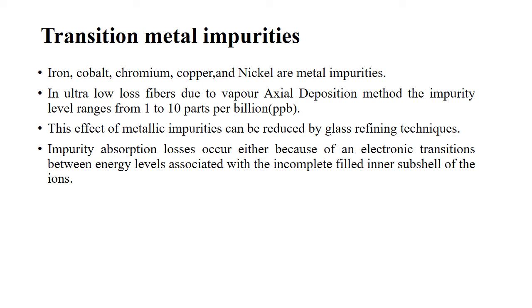The impurity absorption losses occur either because of electronic transitions between the energy levels associated with the incompletely filled inner subshell of the ions, or due to charge transitions from one ion to another ion.